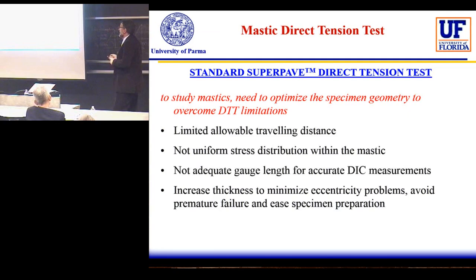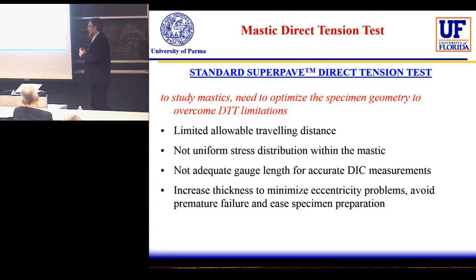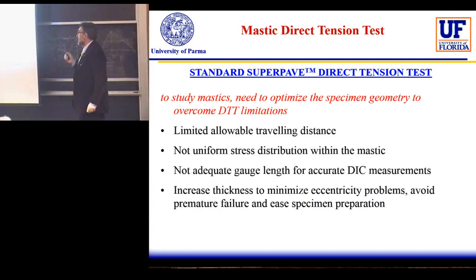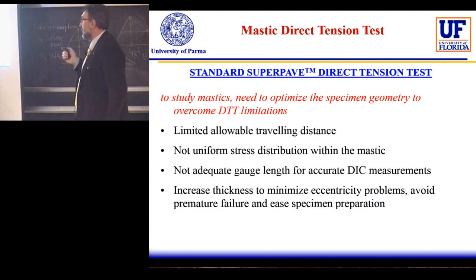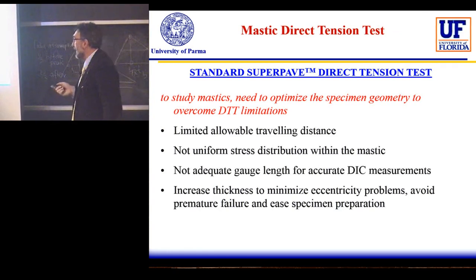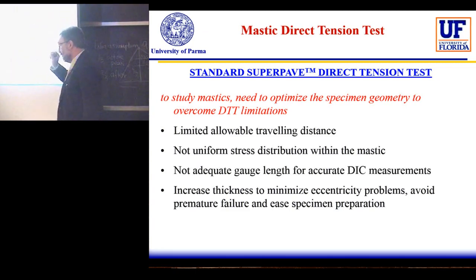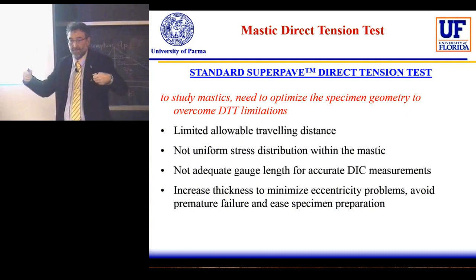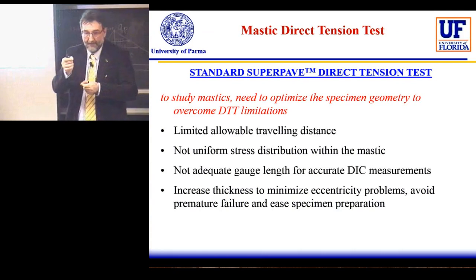Starting the problem looking at the Superpave direct tension test, we had problems with that kind of test because the test setup was not sufficiently big to allow the application of DIC. The stress distribution was not uniform considering the shape of the material. The gauge length was absolutely not compatible with the DIC measurement, and the thickness of the specimen was too small to allow homogeneous results for the test. It was a test designed only to have a level of failure, just a measurement of force, not to understand what's happening in the material during the loading phase.